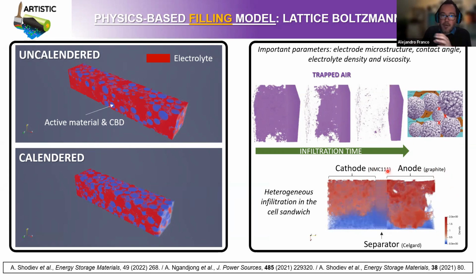You have an NMC111-based electrode on the cathode side. In the middle, you have a separator with a microstructure arising from tomography characterization. And these electrode microstructures were generated stochastically. And you see here how heterogeneous the infiltration process is if you put a drop of electrolyte on top, right? And this is because the porosities and the tortuosity factor of these three layers are different, right? This explains why it's so heterogeneous.